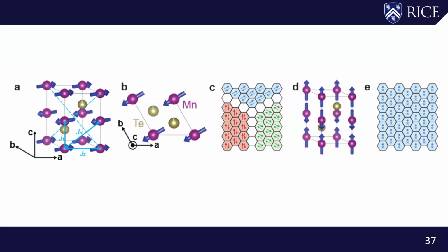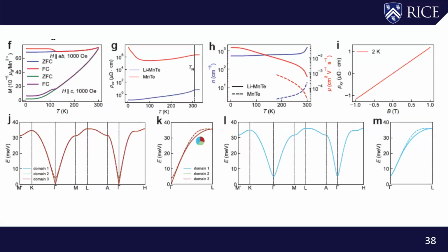And what's really interesting in this particular case is that, although the microscopic origin is not yet known, if you dope lithium into the system, it has been shown conclusively by the Oak Ridge group that the spins of the system rotate from the in-plane direction to the c-axis direction. Also, the amount of lithium you can dope is exceedingly small, about 3%. So once you dope it, you rotate the system from in-plane to the c-axis direction, and then you immediately get rid of what's called the domain issues, right? You don't have these three domains anymore. And in principle, all the conclusions in terms of altermagnets should not be affected by such a doping effect. But in reality, we find it to be quite different.